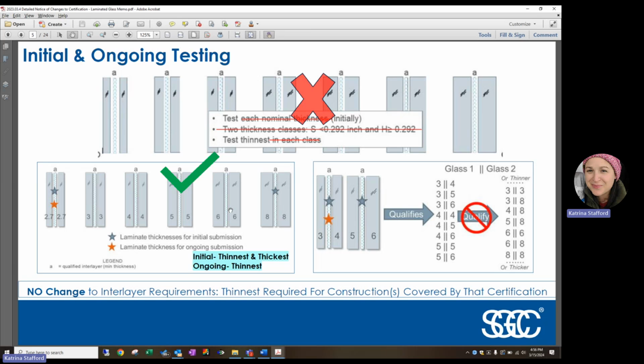So for example, in the bottom left-hand corner here, it shows you that if you send in the thinnest configuration of 2 lights of 2.7 glass with an 030 interlayer, and you send in your thickest configuration with 2 lights of 8 millimeter glass with an 030 interlayer, you're certified for everything in between. Now, keeping that in mind, you can't go thinner than the 2.7 since it hasn't been tested.